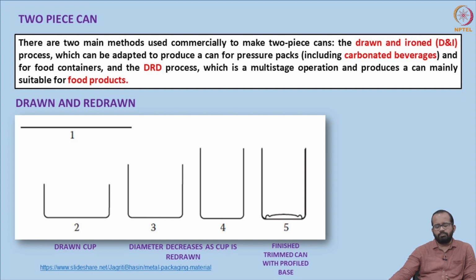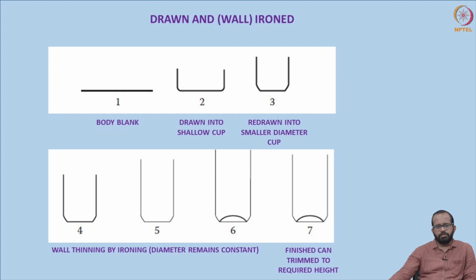In the case of the drawn and wall ironed method, or DWI method, it is basically an extension of DRD. So additional steps are added after drawing. In the case of DWI, or wall ironing, the diameter does not change. Basically, the wall thickness decreases. That is one of the important peculiarities of wall ironing. The thickness of the metal will change from 0.3 mm to 0.1 mm. But the body height usually increases. The bottom will be of the same thickness.